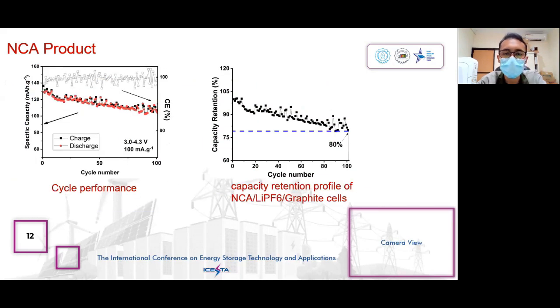The cycle performance of the NCA LiPF6 graphite cell is under the current rate of half C with the operating voltage of 3 until 4.3 volt. Based on the figure, the cell has Coulombic efficiency of about 100%, which indicates good lithium-ion reversibility. However, after 100 cycles, a capacity drop can be observed clearly.